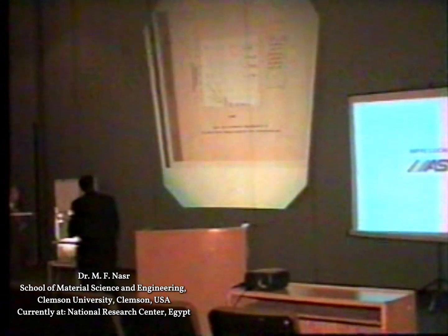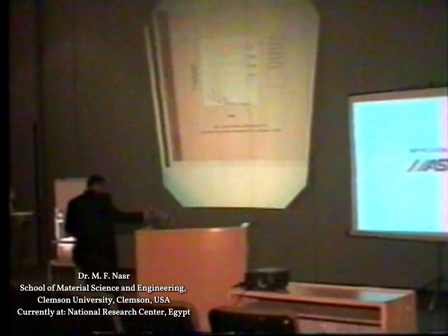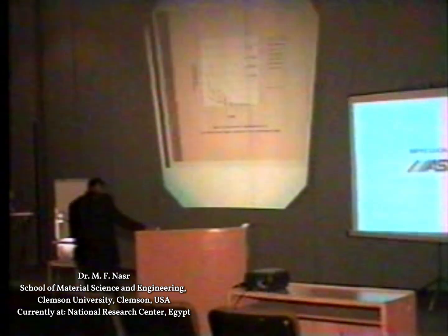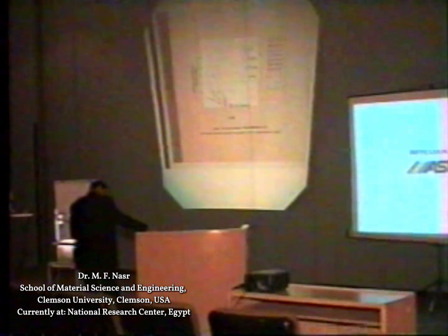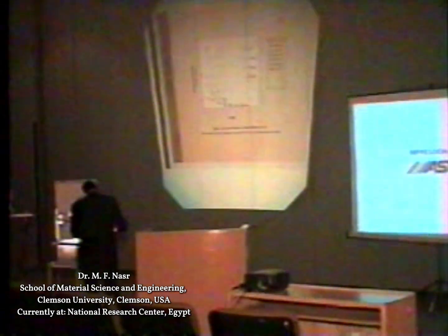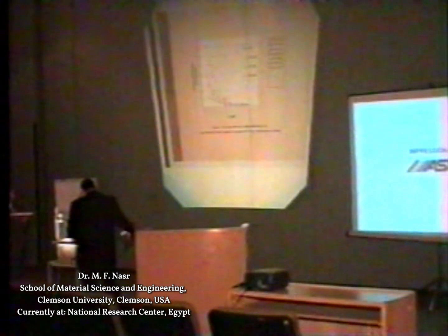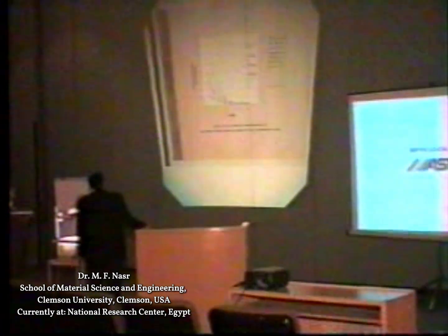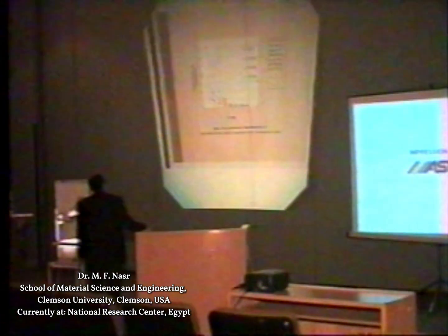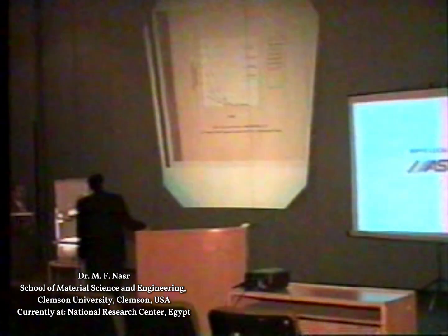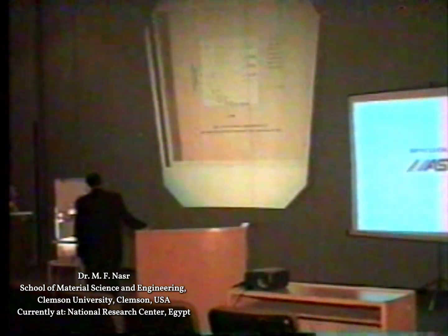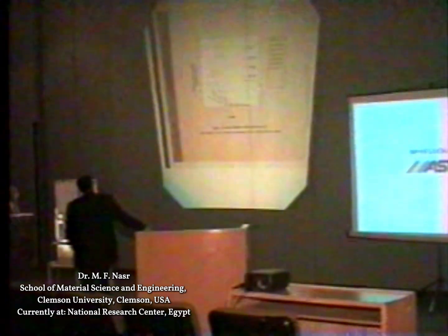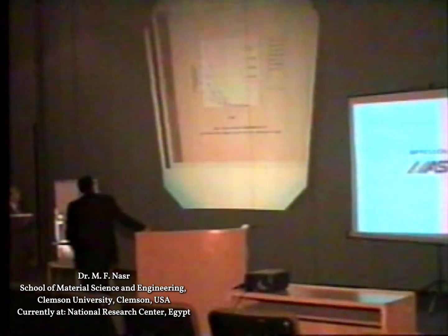And by measuring the volume resistivity against the voltage, we can see, of course, ACF has 720 ohm per centimeter at 0.5 volt compared to about 120 kilo ohm per centimeter for the sample heat treated at 900 degrees. And of course, we see how drastically we decrease the volume resistivity just by doing the heat treatment.